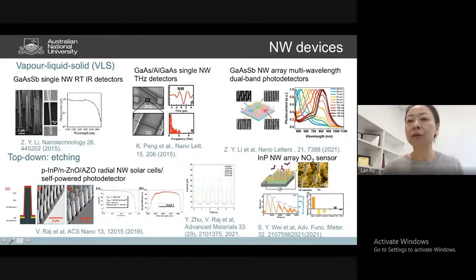We also have shown that if we can design a nanowire array with different thickness and diameter, we can actually change the resonance of the whole nanowire array. The absorption will change, and thereby we can achieve this multi-wavelength photodetector ranging from 500 nanometers all the way to 900 nanometer photodetection. So we grow all these different nanowire arrays with different diameters. We can achieve this multi-wavelength detector.